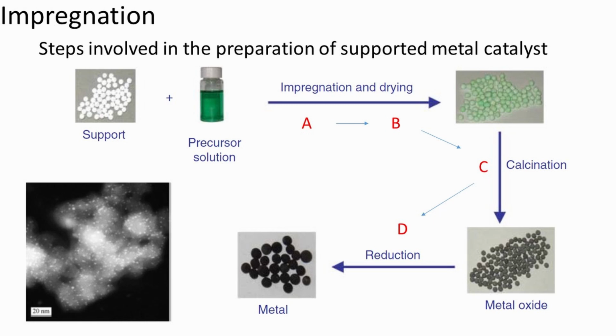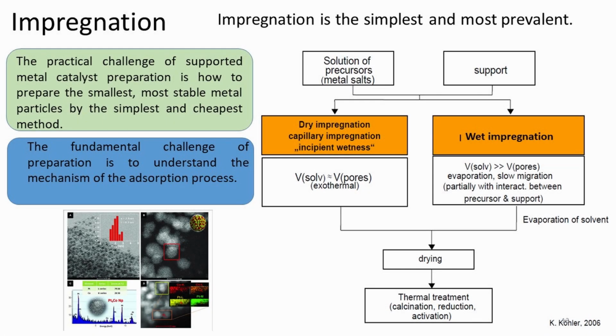So-called incipient wetness impregnation, sometimes called dry impregnation or pore volume impregnation, involves contacting the support with an amount of the solution of the precursor of the active phase such that the pores will just be filled. The pore volume of the support can be determined by nitrogen physisorption or water uptake measurement. If we use more solution than the pore volume, the method is referred to as wet impregnation.